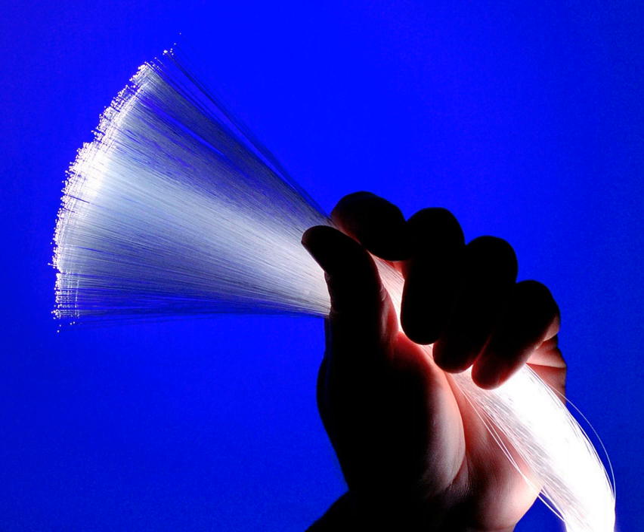The fiber ends are first stripped of their protective polymer coating, as well as the more sturdy outer jacket, if present. The ends are cleaved with a precision cleaver to make them perpendicular, and are placed into special holders in the fusion splicer. The splice is usually inspected via a magnified viewing screen to check the cleaves before and after the splice. The splicer uses small motors to align the end faces together, and emits a small spark between electrodes at the gap to burn off dust and moisture. Then the splicer generates a larger spark that raises the temperature above the melting point of the glass, fusing the ends together permanently. The location and energy of the spark is carefully controlled so that the molten core and cladding do not mix, and this minimizes optical loss. A splice loss estimate is measured by the splicer, by directing light through the cladding on one side and measuring the light leaking from the cladding on the other side. A splice loss under 0.1 dB is typical. The complexity of this process makes fiber splicing much more difficult than splicing copper wire.